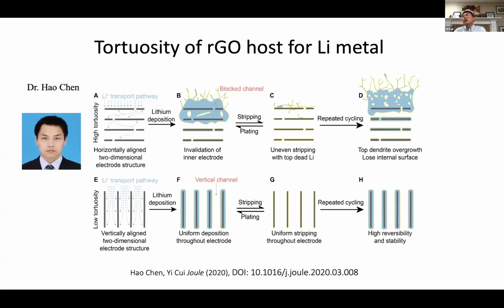We said, well, this graphene oxide, depending on if it's horizontally aligned, you build a battery cell stacked like this, right? And then the lithium needs to go into the host, needs to go around. If you can orient it vertically, this in scientific terms is a tortuosity issue. Tortuosity of vertically aligned will be smaller, will be one. Horizontal will be bigger. The path to go in will be larger.